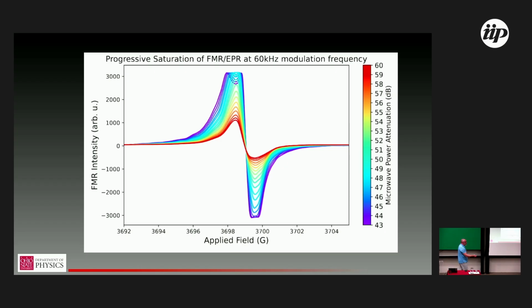So then, of course, the next thing to do is take data at a lot of powers, and that's the plot you can see here. It's hard to resolve any details in this version of the plot, but the main purpose is to show there's a smooth evolution as the power turns up, and when this feature appears in the middle, you see the 2 peaks of the derivative curve, the maximum and the minimum, the derivative of the Lorentzian, move further apart. So there's some broadening effect as well.